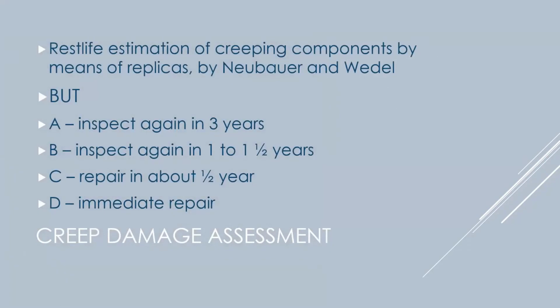And now the method that they came up with at that point is good because you can do this in the field. If you get a modest quality microscope, you can do this on scaffolding right in the field, versus some of the other methods where you're going to have to do quantitative metallography, and that's going to have to be done back in the lab. But this is the beauty of this method, and why after pretty close to 40 years it's still being used.